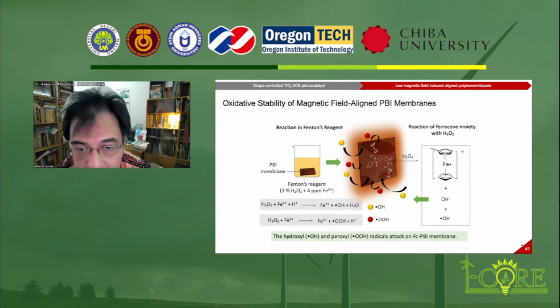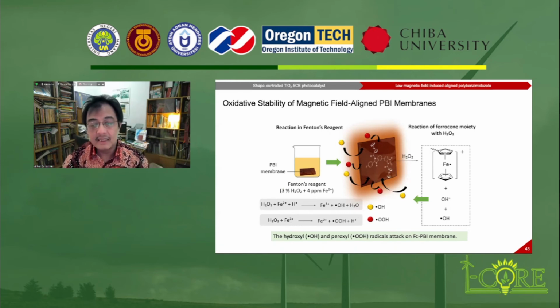We found that a higher content of ferrocene in this study is likely to facilitate the degradation of the membrane. This is because ferrocene possesses an electron donor acceptor conjugated structure with redox reversible characteristic, which could enhance the generation of free radicals from the activation of the hydrogen peroxide. This phenomenon makes the membrane vulnerable to oxidation or degradation.